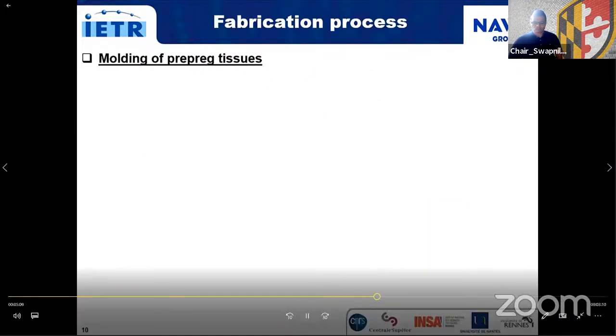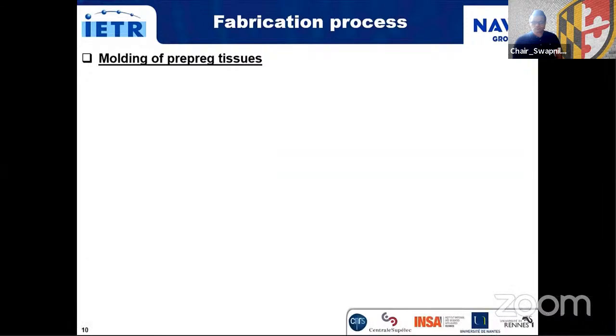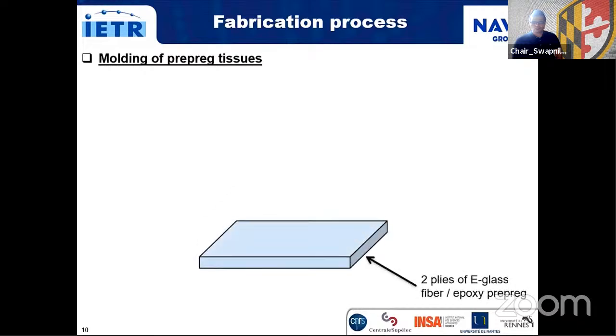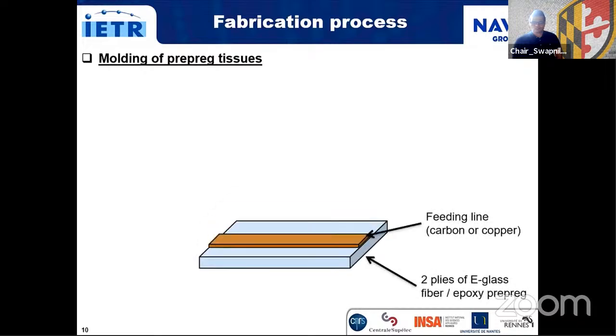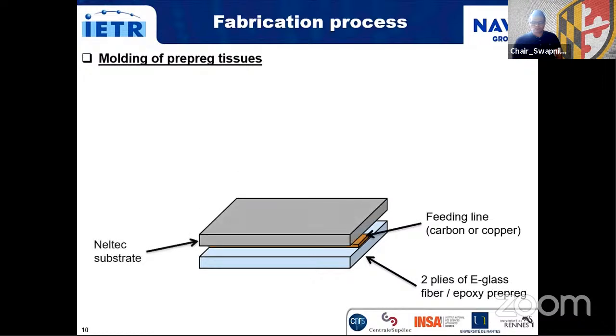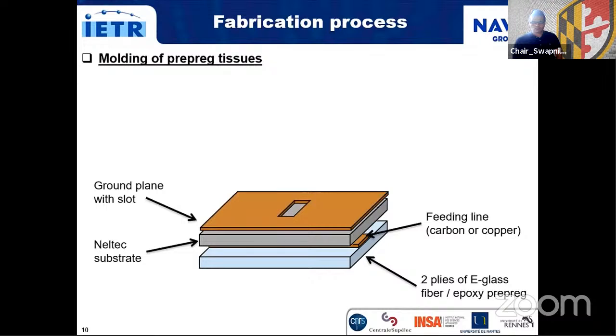Afterwards, the two sandwich-structured composite antennas, a full composite antenna with carbon fiber tissue and the reference one with copper sheet, were fabricated by molding prepreg tissues. First, two plies of e-glass fiber epoxy prepreg were laid on a glass slab. The Neltec substrate with the feed-in line in carbon or copper on one side and the ground plane with the slot on the other side is placed above.